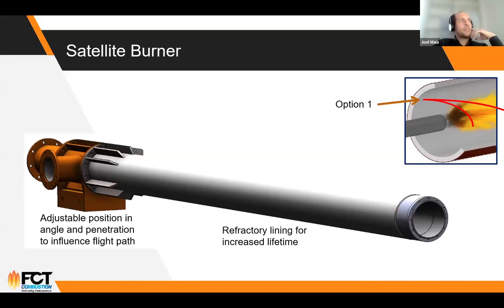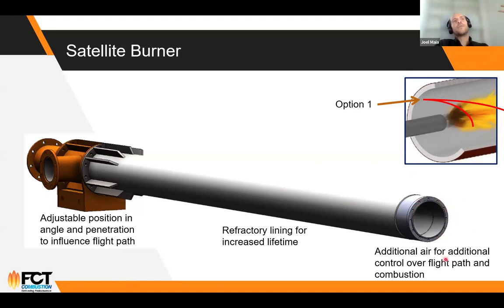Also, this pipe has refractory for increasing the lifetime, and at the front of the satellite burner, you have an additional injection of air through these holes, and this is to give you additional control over the flight path of the particles as well as the combustion. The main advantage of this type of satellite burner is that as you are injecting the alternative fuels before they come to the main flame, there is a time between the injection point and the start of the combustion of this alternative fuel, so you have a pre-drying while this alternative fuel is flying. You also have a preheating because the alternative fuel is being injected into a 900 degree environment.